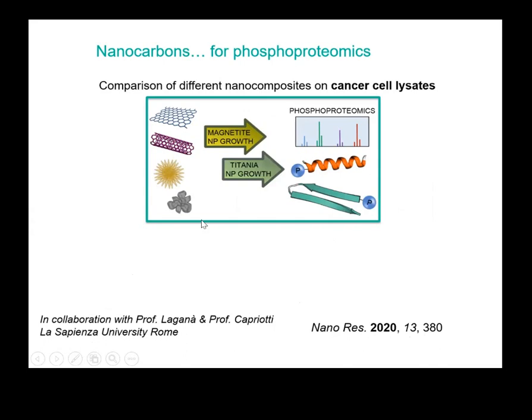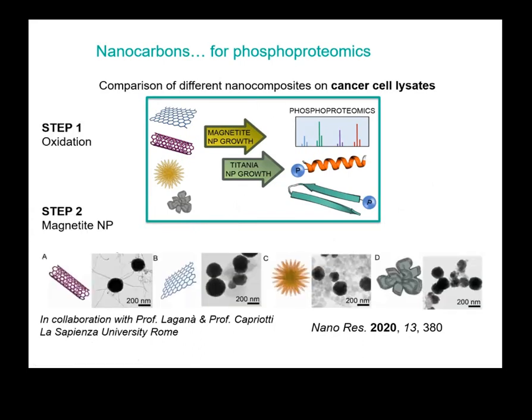So in this work, we compared nanocomposites with different nanocarbon morphologies. So we had graphene, carbon nanotubes, nanohorns, and graphitized carbon black. And we magnetized the materials, and then we grew titania, nano-sized titania, on top, and applied them in phosphoproteomics, as mentioned. And in the first step, we oxidized all the carbon nanomaterials to the same extent to allow for their improved dispersibility in biological fluids. And then we grew magnetite nanoparticles on top, and we didn't really see a big effect of the different nanocarbon scaffolds on the morphology or physicochemical properties of the nanoparticles.